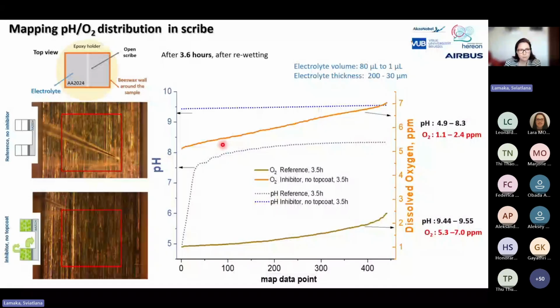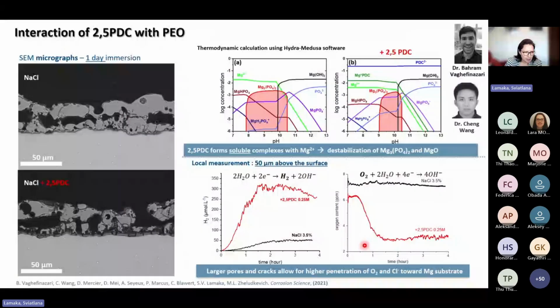And so then we thought, if it's so, and if indeed this barrier layer is disrupted, then we should be able to see strong oxygen reduction on this magnesium sample. And then the local measurements were performed, and we traced the concentration of dissolved oxygen and dissolved hydrogen simultaneously. And indeed, in the presence of pyridine dicarboxylate, we see significant depletion of oxygen locally at the sample interface, and also stronger hydrogen evolution, which means that pyridine dicarboxylate indeed disturbed the barrier properties of this PEO layer.